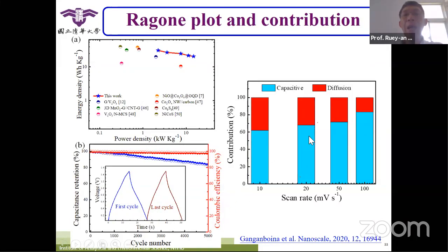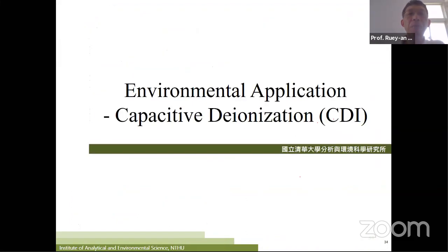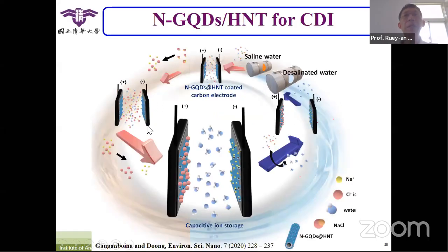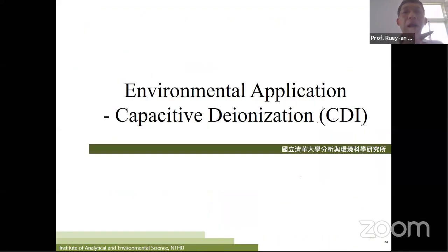Here we analyze the contribution of the diffusion and capacitive. We always will see that when you use the high scan rates, the capacitive contribution will be much higher. It means that the GQD actually plays a very important role here. So not only for energy application, you also can use these materials for capacitive deionization for environmental application. The idea is the same. Capacitive deionization, their principle is very similar to supercapacitor. They just store electrons getting inside, and then we just change the electron into those ions, sodium ion and chloride. So the principle is the same.